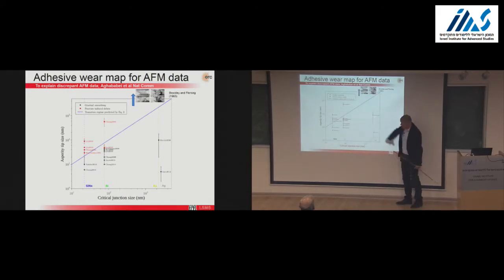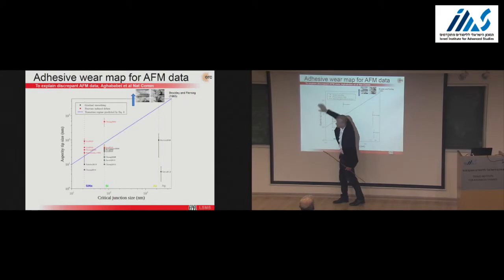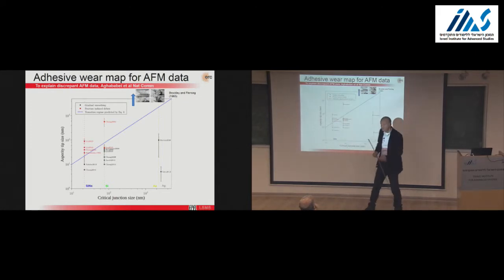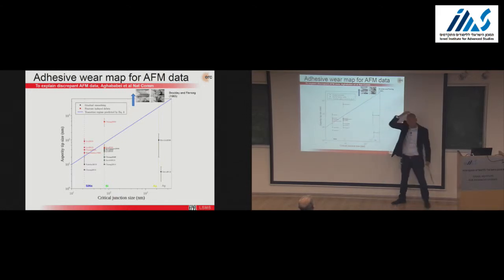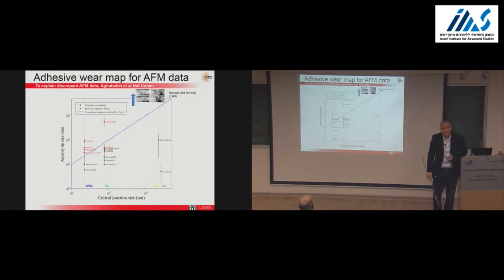For metals, gold, silver, the AFM data we found is way below this transition length scale that we expect to be of the order of micrometers. We do have data from the 60s at scales way above, centimeters, and this is a call for experimentalists to zoom in on this area to see if we can refine the estimations and our understanding for metallic junctions at micrometer sizes.